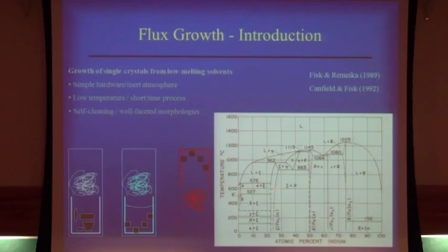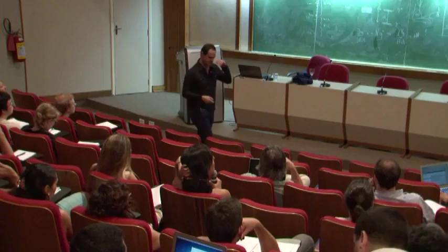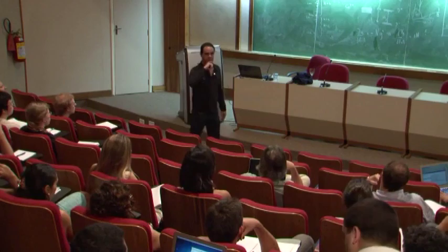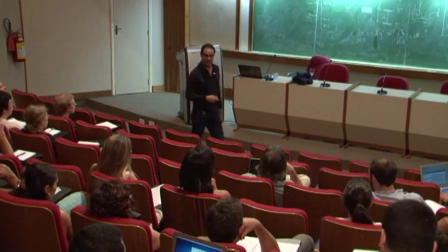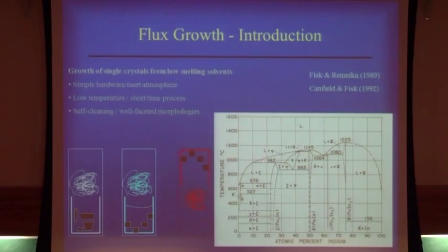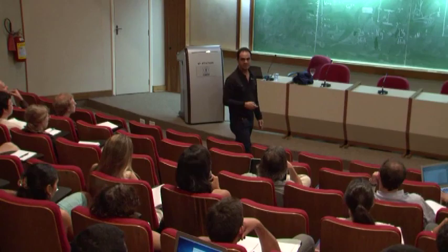They measure that temperature by, for instance, differential calorimetry. Differential calorimetry to get the right enthalpy of formation for all the phases, and we can do that. And we can map the temperature and the amount of indium in plutonium that you are, you know, here is plutonium, right? So you can do the mapping, determine this temperature by differential calorimetry, and map the stoichiometry with the temperature for each phase, experimentally. So then that's the enthalpy of formation of each phase, that you can measure directly.